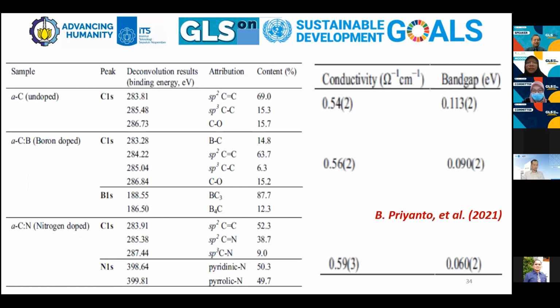Based on the spectroscopy analysis, in 3 samples grown on an ITO-coated glass substrate, bonding between carbon and nitrogen, like this one, carbon and nitrogen, and also carbon and boron is created in the sample. The doping result also slightly changes the electrical conductivity and also the electronic band gap of the sample.